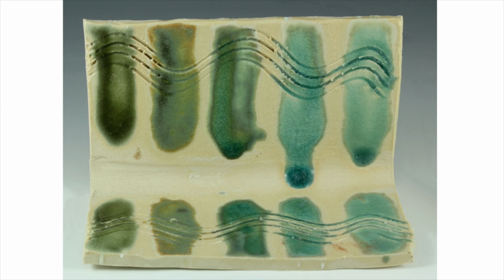In this example, I used a very simple base glaze, just nepheline syenite, 100%, with 2% copper carbonate. That base glaze is the far left stripe. Then I added 10% increments of an influencing ingredient to see how it affects that base glaze. I like the middle stripe, so I chose that stripe with that recipe to mix up and then glaze this bottle.